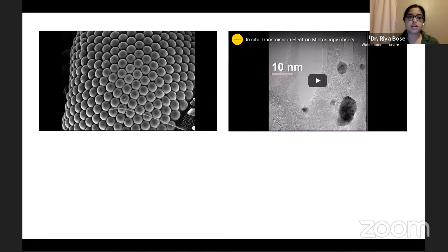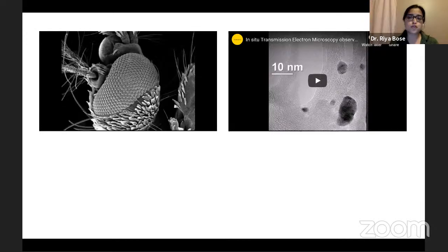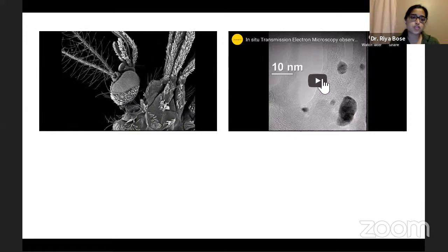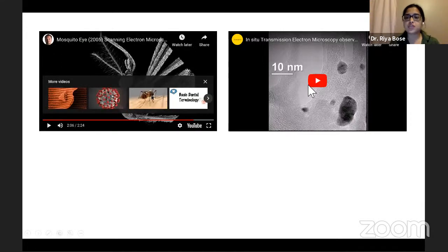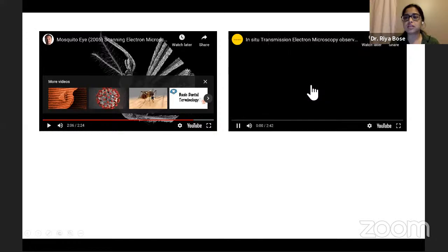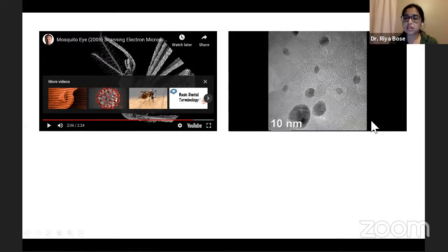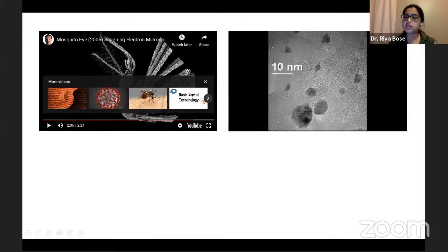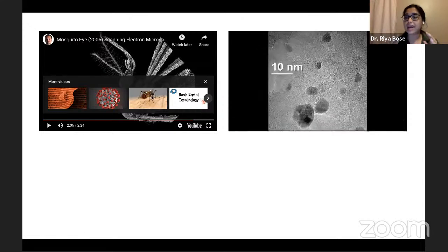So as we can see, this microscopic world is indeed very fascinating. So I will stop this and I will show you this video, which was taken in situ inside a TEM machine that is actually using liquid cell TEM. So basically the sample is in liquid form, and what you can see is that two silver nanocrystals here are coming together and they will coalesce with each other. And with the scale bar, you can see the size is 10 nanometer.